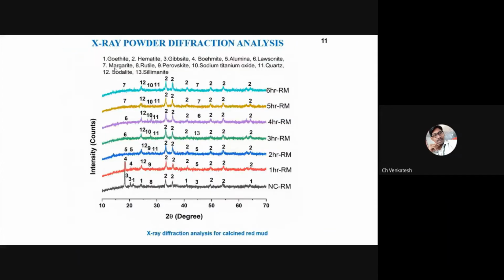So coming to the X-ray diffraction analysis, in the present study we need to know how red mud changes its transformation with respect to temperature. So for that, we conducted the X-ray diffraction analysis. You can clearly observe here that at 0 hours, goethite, hematite, gibbsite, and boehmite were present.